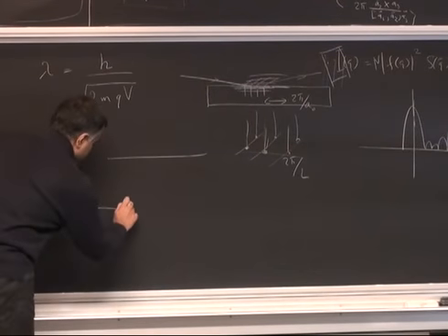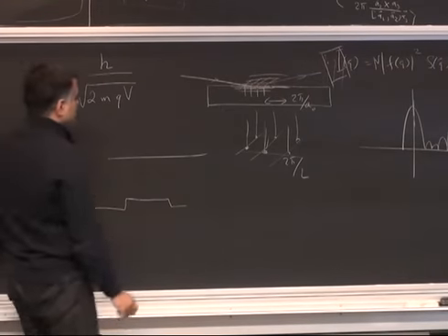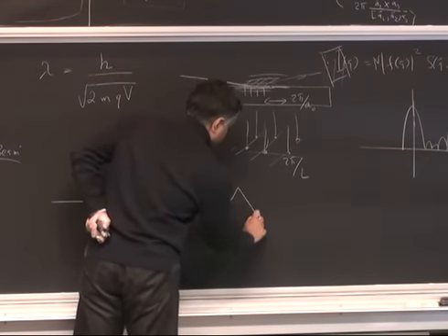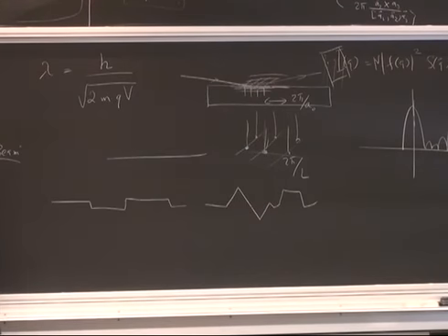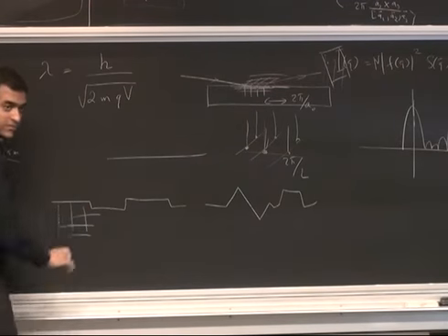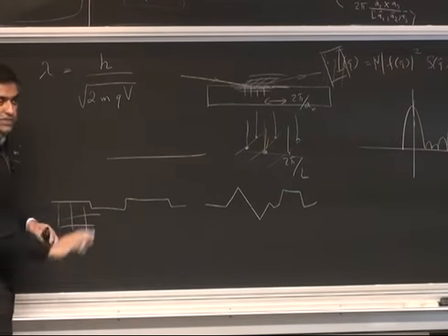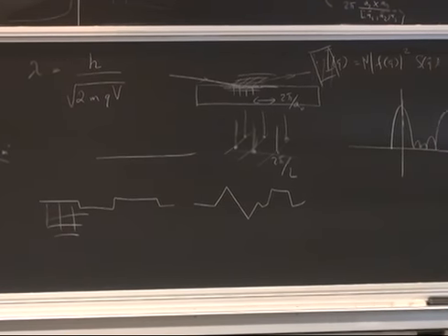If your surface is mostly smooth, but it looks like there are atomic steps, you get streaks. But if your surface looks more like there is some roughness to it, then that's what you get. Remember that this whole thing is still a single crystal. It's just the surface morphology that is modifying the diffraction spots into these patterns.